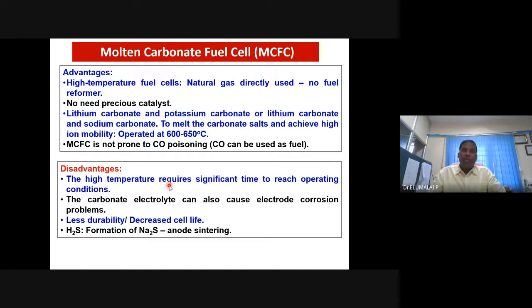But wherever CO emission is there, this fuel cell can be adopted very much. You don't need to separately generate CO and feed it to the MCFC cell. But wherever CO is emitted, maybe along with the CO2, this fuel cell can be very much used. So MCFC or molten carbonate fuel cells is one of the high temperature fuel cells. Fuel hydrogen can be very much used. Carbon monoxide also can be used. You don't require precious catalyst. Even nominal catalysts like nickel chrome will do. So you don't need to have a precious catalyst. That is one of the merits.